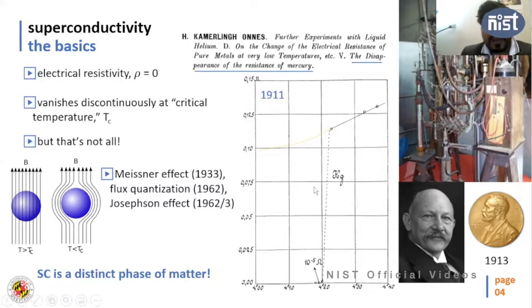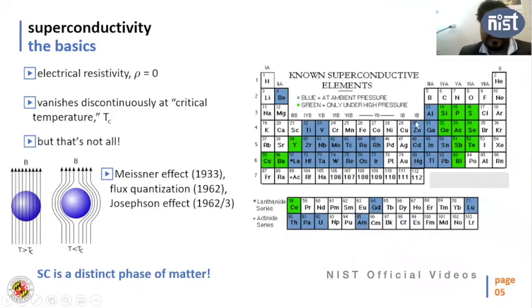However, if you apply a high enough magnetic field, it is possible to restore the resistive path. What I mean is, if you apply, let's say, a magnetic field H which is quite high, higher than the critical field, then the resistance will behave like this dotted line. These are the two things discovered by Kamerlingh Onnes. The first, in 1911, was the vanishing resistivity. The next year, he found that if you apply a magnetic field, you can restore the resistive path. Due to this discovery, he got the Nobel Prize in 1913.